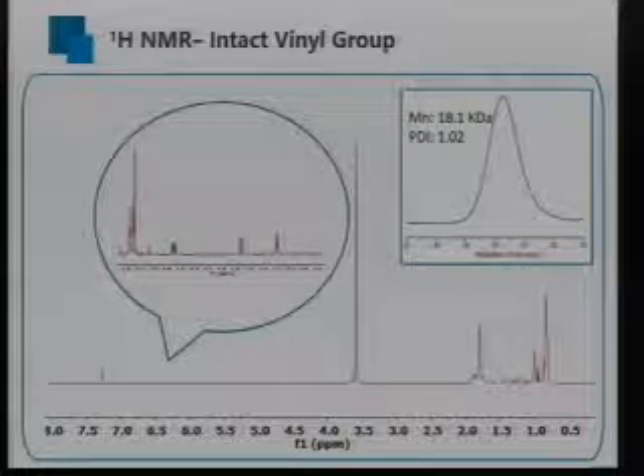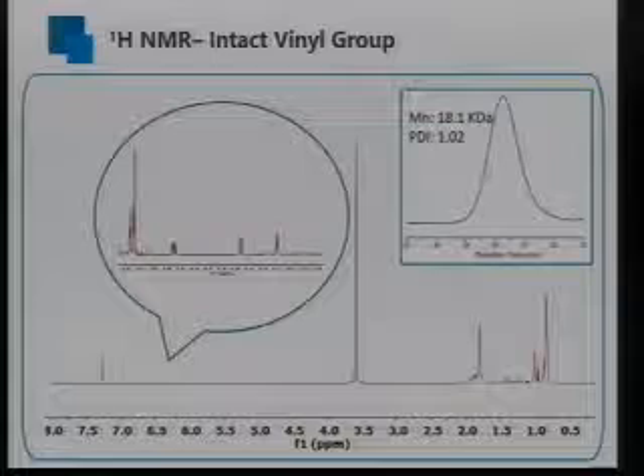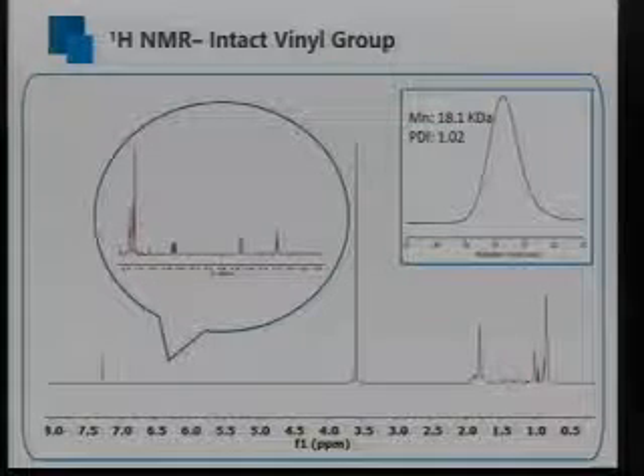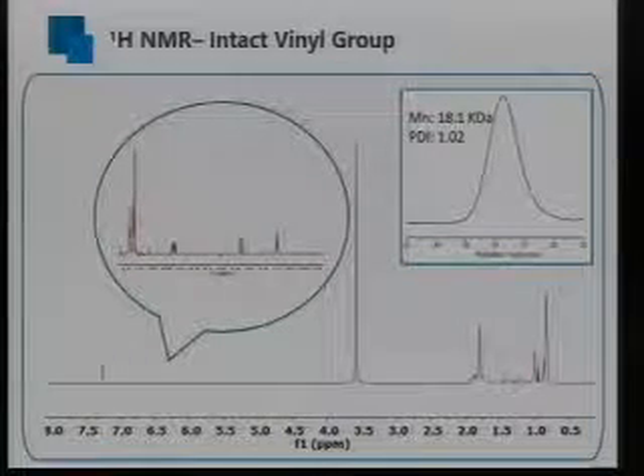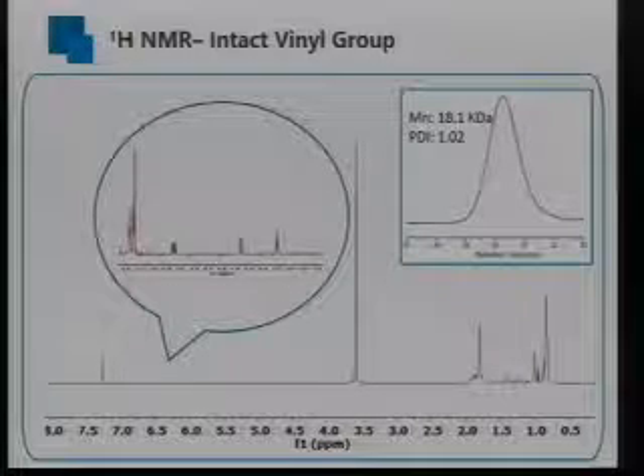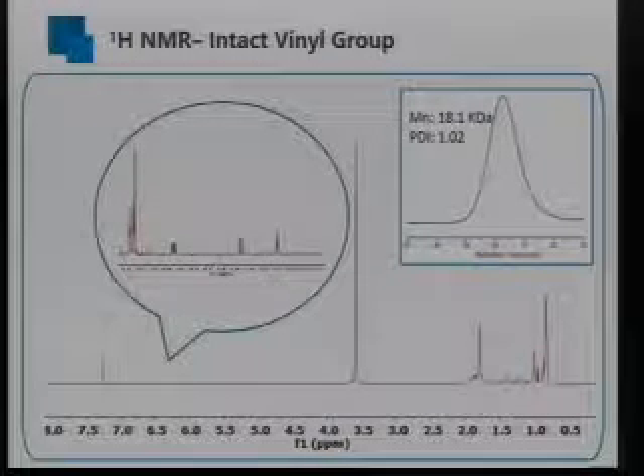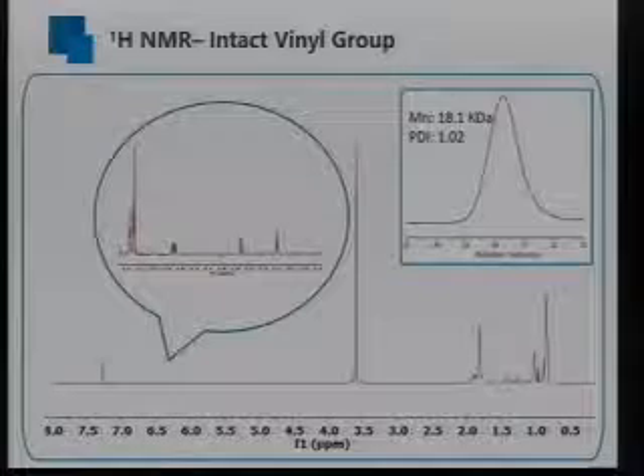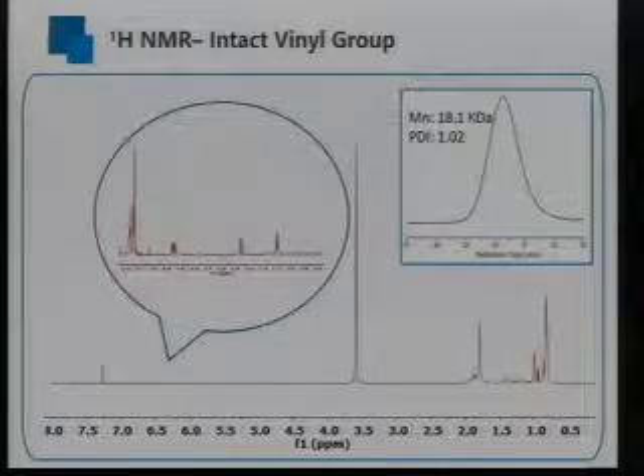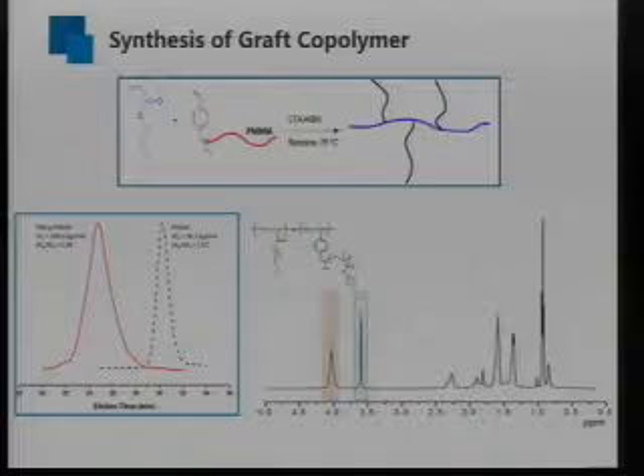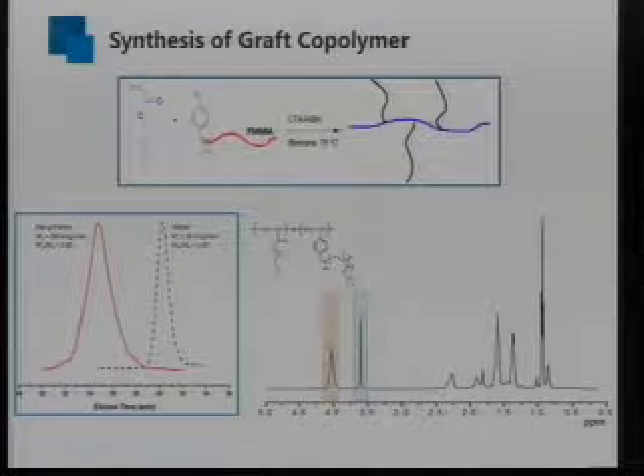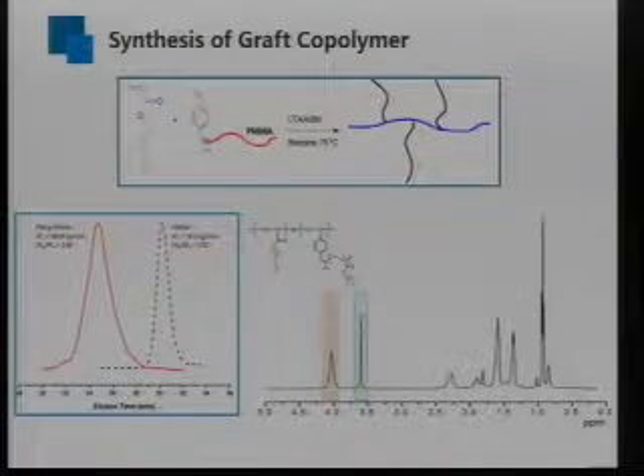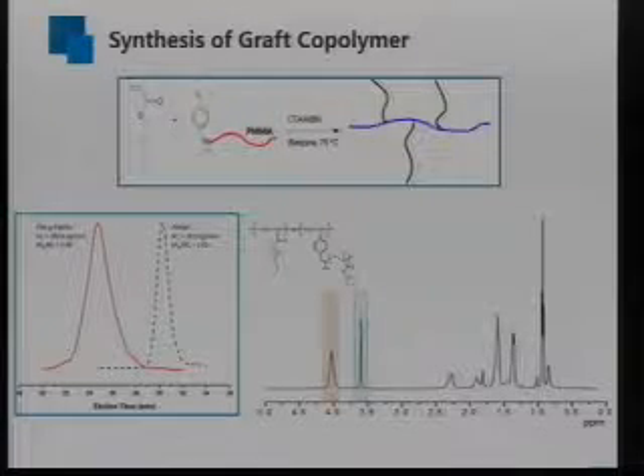By anionic polymerization, the PMMA macromonomer was successfully synthesized with a polydispersity (PDI) as low as 1.02. And by NMR, we demonstrate the intact vinyl group after the polymerization. This PMMA macromonomer was then copolymerized with butyl acrylate by controlled radical polymerization to make the final graft copolymers. And from the GPC trace, we can see the clear shift from the PMMA macromonomer to the final graft copolymers,